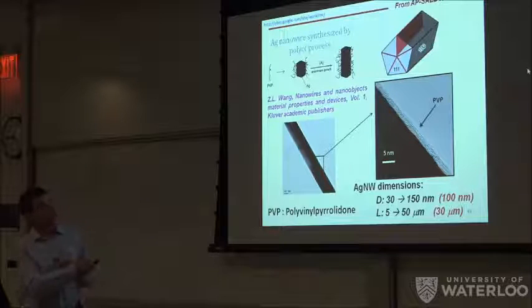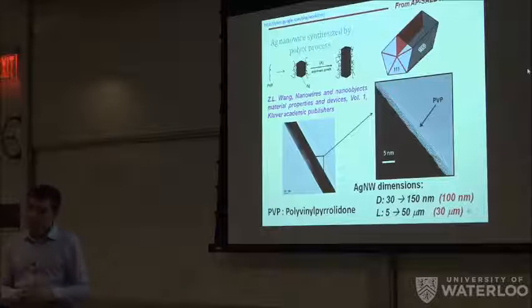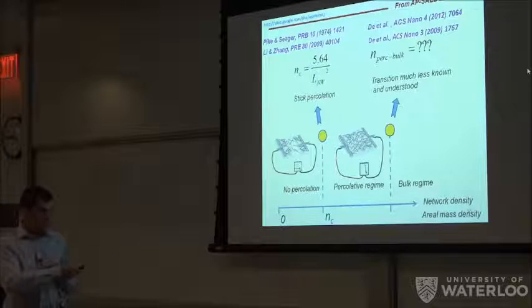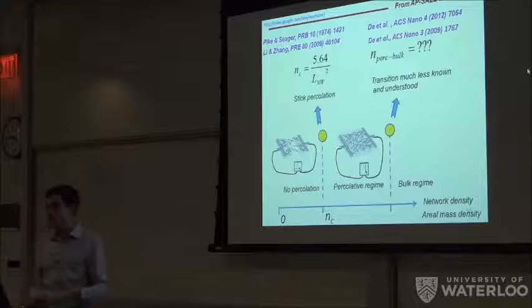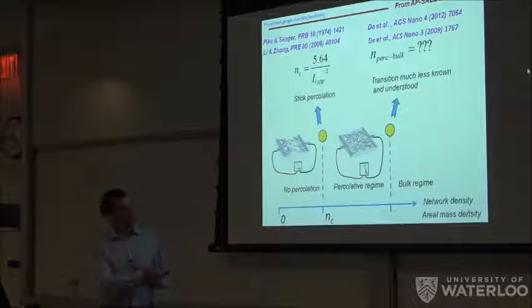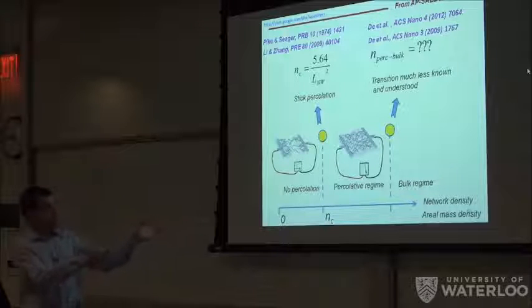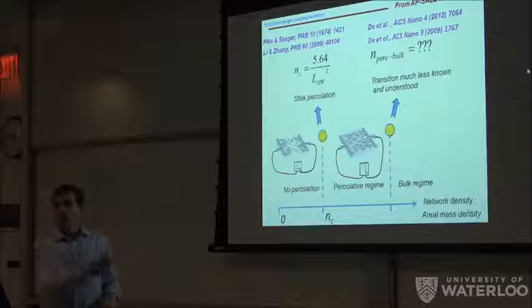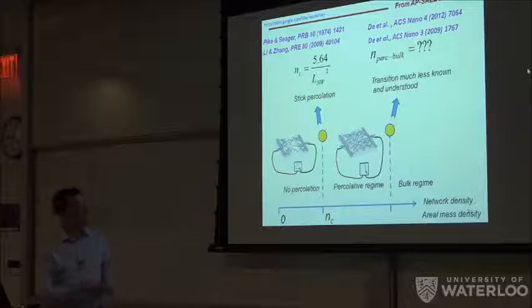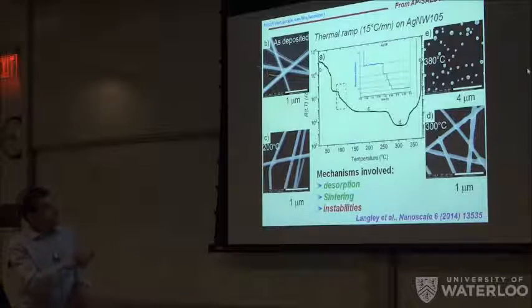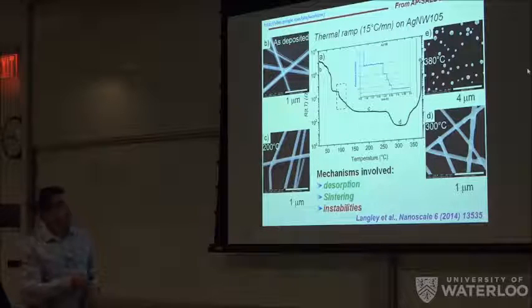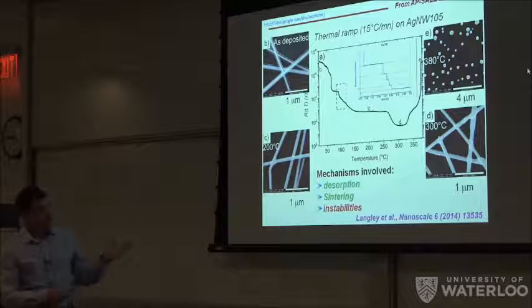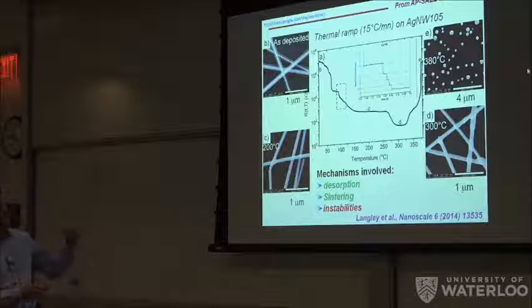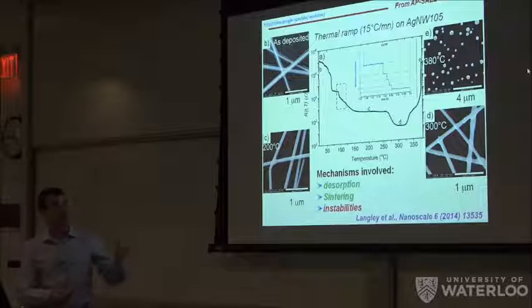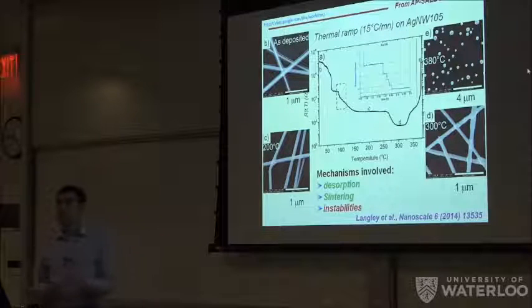And we get these silver nanowires with this pentagonal shape commercially. We purchase them, we deposit them, and then we try to measure the properties to optimize it, to model the behavior, and then to understand what happens between this stage of no percolating network to this percolating regime where you have current flow, and what happens beyond that. And the way we do it, we deposit the nanowires, and then we need to do a heat treatment to enhance the junctions between the wires. And once we reach an optimum temperature, the resistivity is optimized. And if you continue heating, you're going to have this Rayleigh instability, and your wires are going to spheroidize.